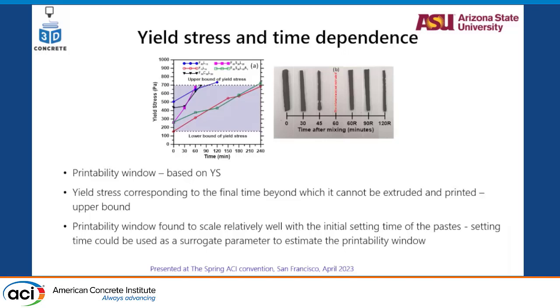But we also did remixing. So you see here at 0 minutes, so immediately after mixing, you could extrude. After 30 minutes, you could extrude. 45 minutes, you could not. But what happens if you remix after 60 minutes? Do the same thing, remixing.